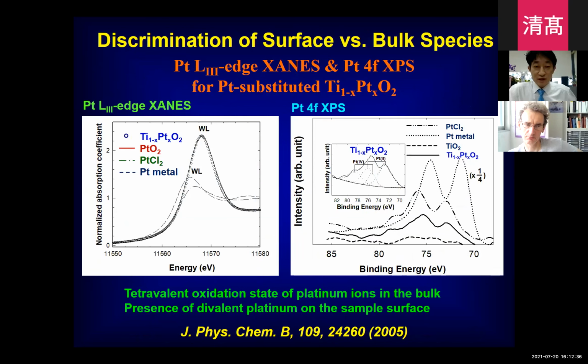We studied the bonding nature of the platinum ion stabilized in rutile TiO2 structures. From the XAS, we can get very, very strong spectral similarity between the PtO2 and the Pt-substituted TiO2. So it is very strong evidence for the tetravalent oxidation state of the substituted platinum ion. But if you study this material by using the XPS, as you can see here, we observe the coexistence of platinum 4+ and 2+. So based on that, we can interpret this discrepancy as evidence for the stabilization of platinum 2+ on the surface.